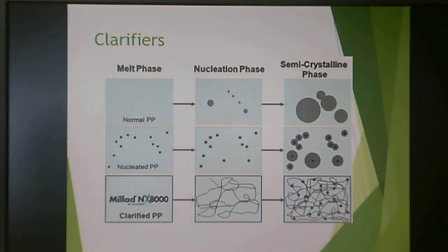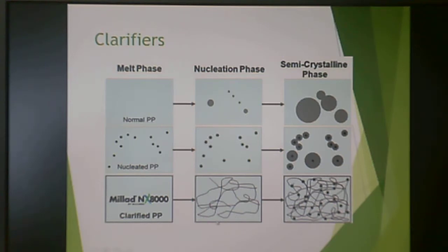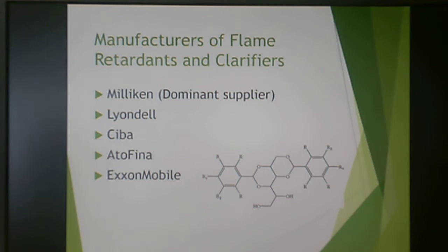Here is a normal polypropylene, a nucleated polypropylene, and a clarified version. If you have something that's nucleated, you get smaller crystallites — the large ones will definitely scatter light. With clarification, you get crystallization similar to nucleation but the crystallites remain very small, so the material remains clear while still having crystallization present and some increase in tensile strength. A wide variety of manufacturers produce these clarifiers — ExxonMobil makes quite a bit, and Ciba is another one to work with.